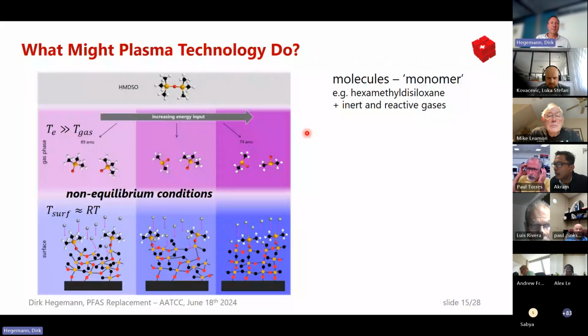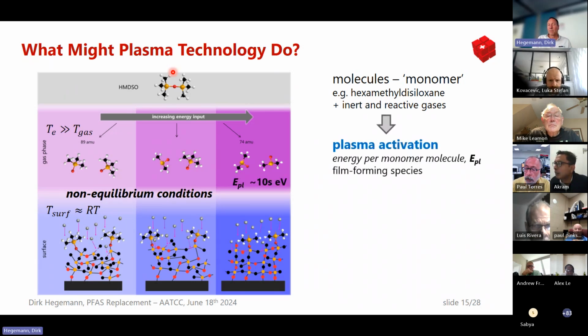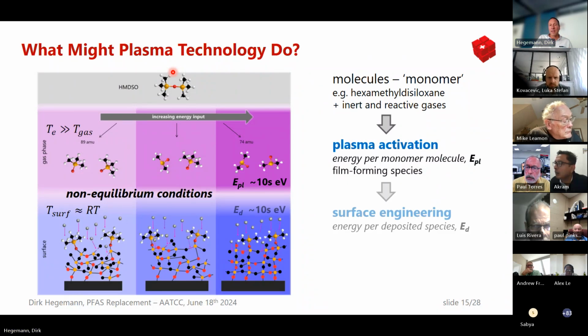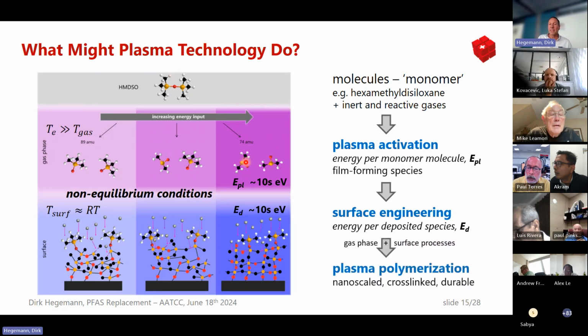Good. Okay, now let's look at what we might do with plasma technology. So, of course, we can also use these small molecules of siloxane and bring them into the plasma. Plasma is a reactive ionized gas where you activate your monomer depending on the energy you have. And those activated molecules then diffuse to the surface, and surface engineering can also be done by supplying energy. And finally, you have a deposit, so you grow what we name a plasma polymer film.